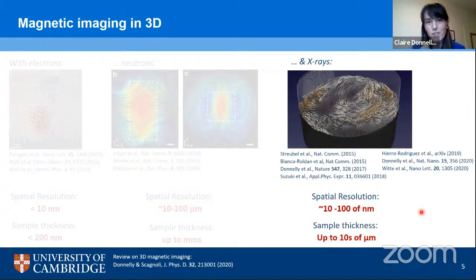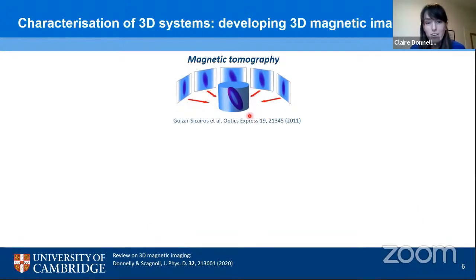So before I go on to the next step of our results, I'd like to first of all introduce the concept of X-ray magnetic imaging of three-dimensional magnetic systems. And first of all, I'd like to introduce the concept of tomography. So here we're talking first of all about non-magnetic tomography, where the idea is that we have some sort of 3D structure. We measure two-dimensional projections of this structure with high resolution for many different sample orientations with respect to the X-ray beam, as you can see here. And then we recover the internal configuration by using a reconstruction algorithm. And this is very similar to what happens in a CT scan in the hospital.